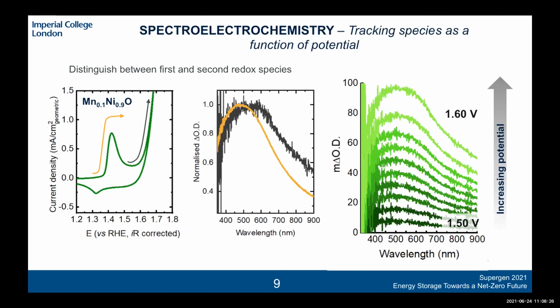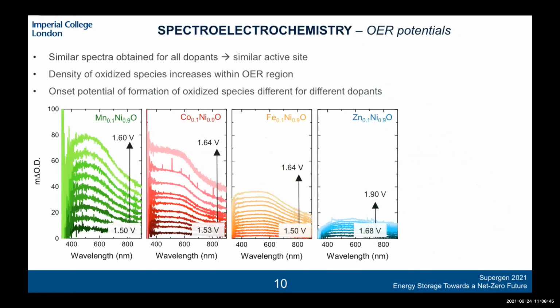We can also quantify the density of these species. So as we increase the potential from about 1.5 to 1.6 volts, we see that the density of these second oxidized species increases as a function of potential. So while this is specifically an example of the manganese doped nickel oxide, we see that across the spectrum of catalysts that we've studied here, we have a similar growth in these species as a function of potential. But what's different is that in the case of the manganese doped oxide, these are formed at relatively low potentials of about 1.5 volts, whereas looking at the zinc doped catalyst, you need about 200 millivolts higher, about 1.68, 1.7 volts to trigger the formation of these oxidized species.